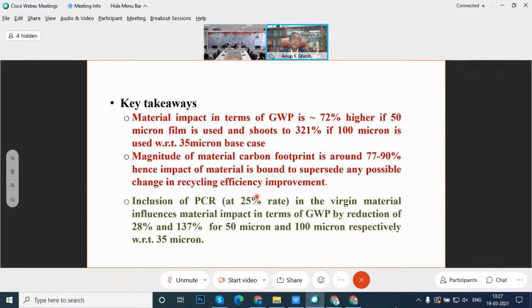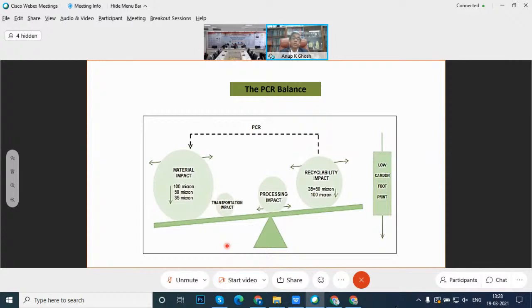And if we can increase this 25% to 50%, most probably we'll be able to come very close to offsetting this 300% increase in environmental load, and we may offset it by reducing it to maybe 250%. So we have to look into this and we have to balance, and this should give a policy document, a policy suggestion, why we should go for 50 and why we should go to 100 and why we should be going above 100 for this purpose, until and unless we have a proper recycling back and replacement of the virgin material. Just increasing the thickness, I don't believe gives a proper solution for this.